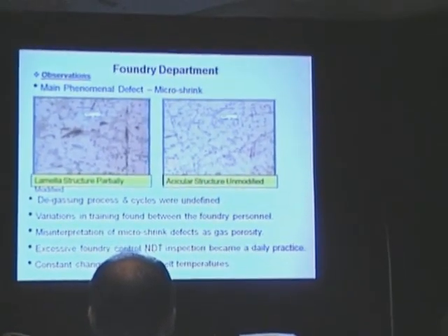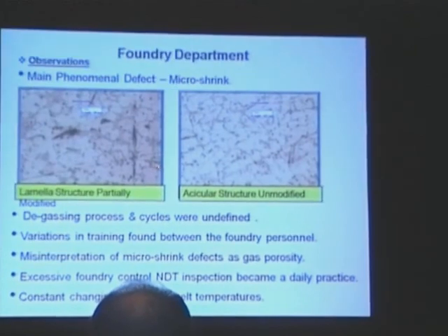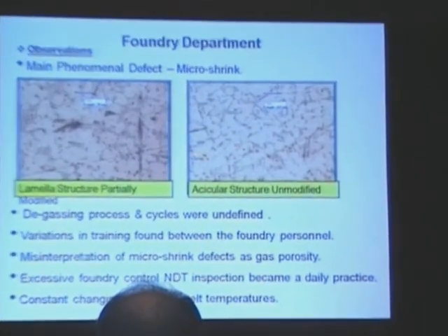So I'll take you a little bit inside, and we're going to dive straight into the foundry, and I'll give you some of the topics, the stuff we did in the foundry department. So the first observation that we recognized is that our main phenomenal defect is microshrinkage. You can see on the pictures on the left, the lamellas, a partially modified structure, in which you can see the microshrinkage behavior even worse. And then on the right, you can see an acicular structure, which is an unmodified structure, but at least it's stable. And you can predict what's going to be the outcome.